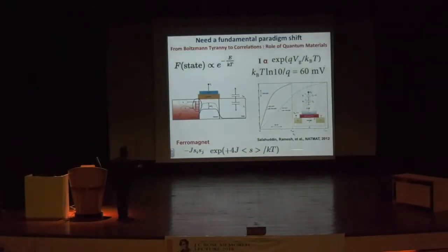This is actually a review of a paper that one of my colleagues, Saif Salahuddin, amazingly smart guy, proposed maybe 10 years ago, using a ferroelectric in series with a MOSFET to create something called negative capacitance. And by using a negative capacitance, you can reduce the slope from 60 to 50. By simply going down by 10 millivolts, you can gain 3 orders of magnitude or so in energy reduction. So it's very important that the slope becomes as small as you can.